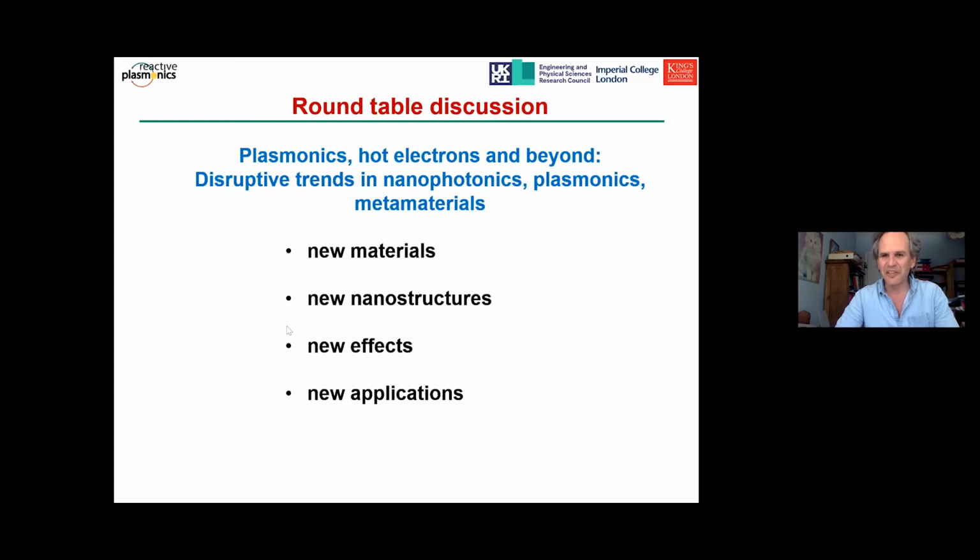And a lot of money is going into this. I don't know if people can comment on where the Rice activity has got to now, since they were first along in terms of commercialization. So the Rice activity, I think in summer 2019, they concluded a major study on prostate cancer, about 50 people or so, using their gold nanoshells of just the right size so that the body can actually get rid of them. At least the press release at that time said that was very successful.